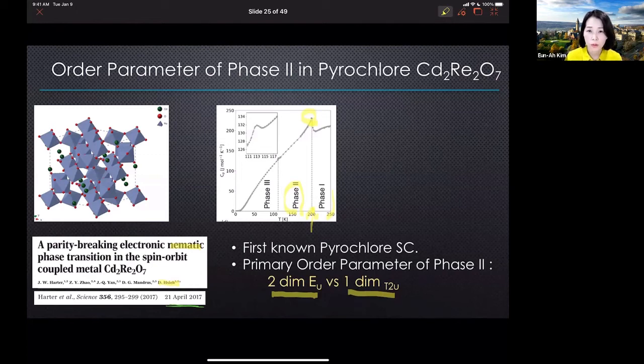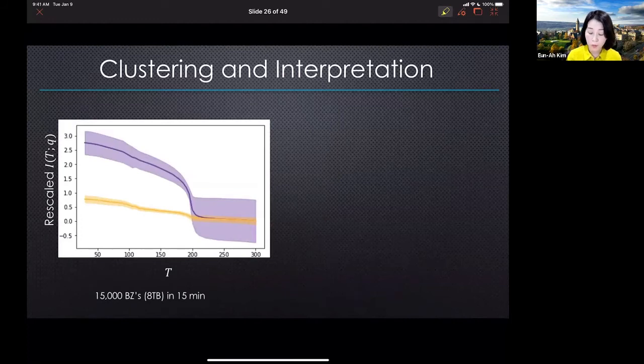So setting out to see whether there was anything missed and to leave nothing unturned, we analyzed 15,000 Brillouin zones, 8 terabytes of data. The XTEC algorithm analyzes that volume of data in 15 minutes. And the result is very simple. If someone showed me this plot and said it is the result of analyzing 8 terabytes of data, I would have had a difficult time believing it. But it looks very simple, and there is clearly something familiar looking here.